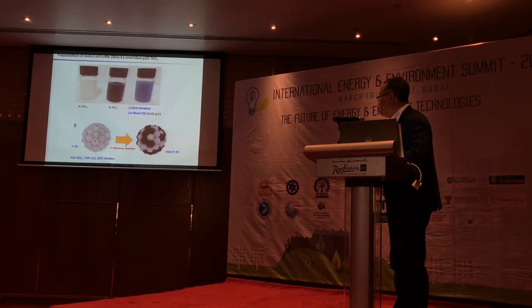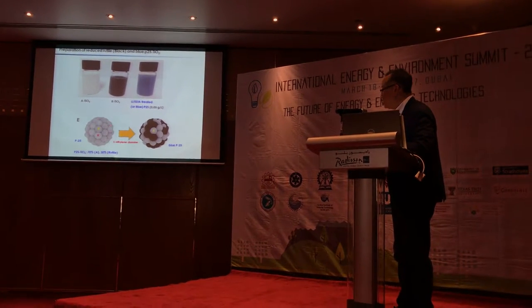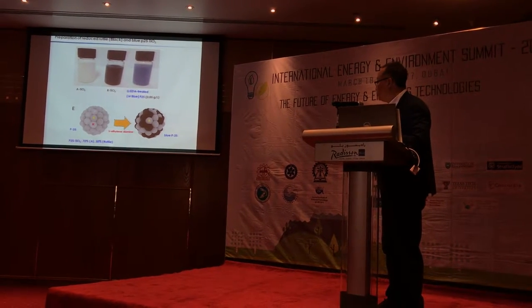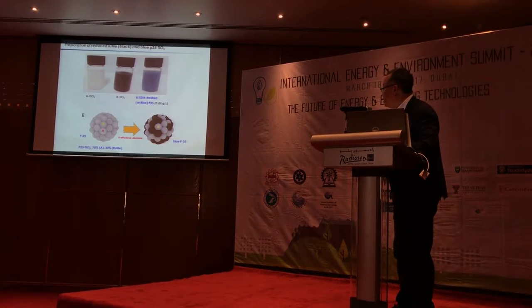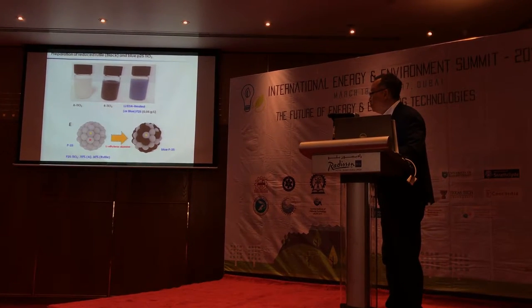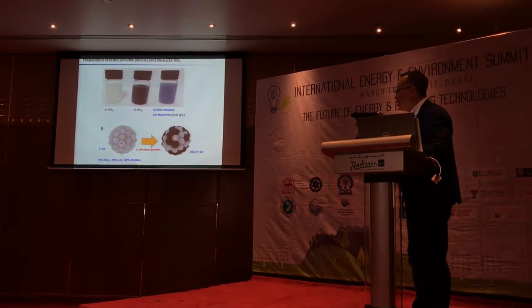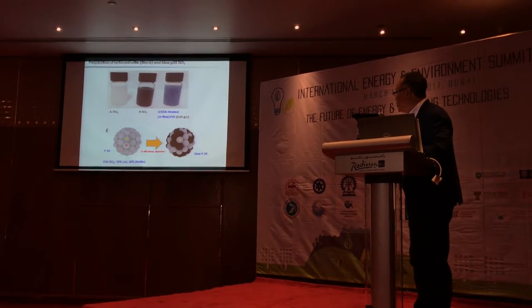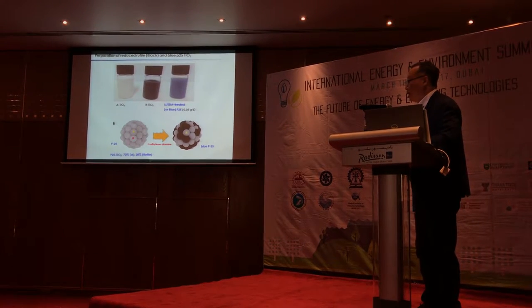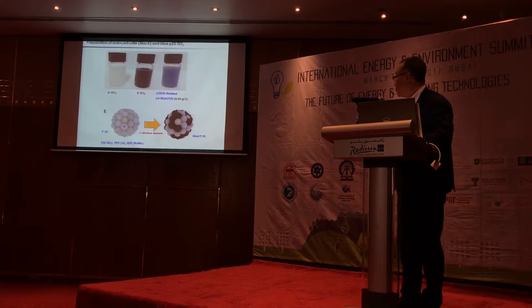Our reagent, lithium ethylenediamine, can selectively reduce — changing only the rutile phase. This is the new material made at room temperature via solution process. If you treat the starting material with anatase alone with lithium ethylenediamine, it did not change. But if you use 100% rutile phase, it makes the black one. And if you use P25, consisting of 70% anatase and 30% rutile, it gives a blue color. Making this blue color is the first time in the world.